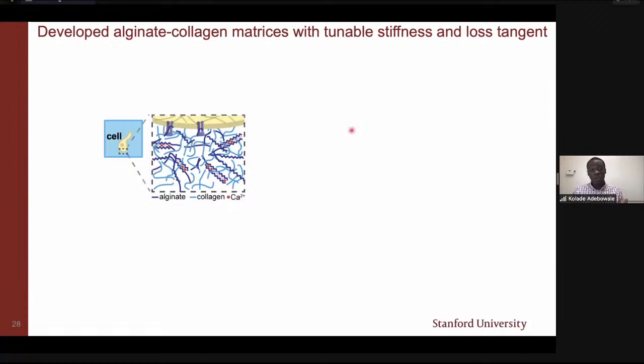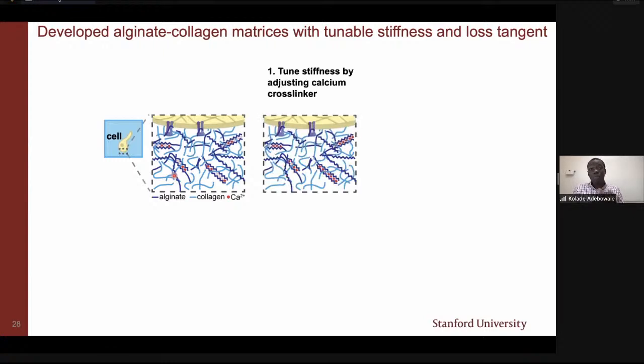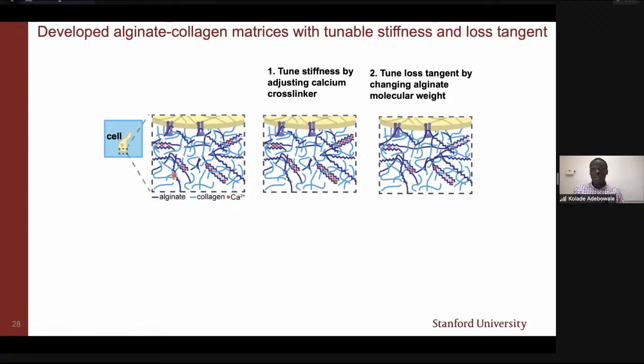So in this part of the talk, we developed an alginate collagen system with independently tunable properties. The collagen is shown by these light blue lines in this schematic, and that's what the cells can potentially bind to. And the second component is alginate, shown by the dark blue lines, and this alginate is ionically cross-linked by adding calcium ions. And we can modulate the stiffness or the Young's modulus of this material by adjusting the calcium cross-linker concentration. We can also tune the loss tangents in the material by changing the alginate molecular weights.